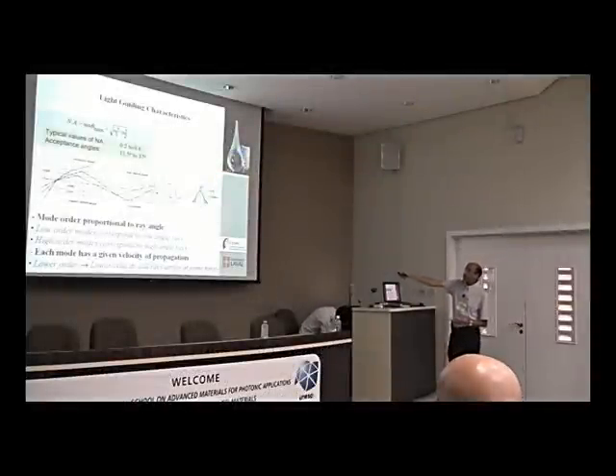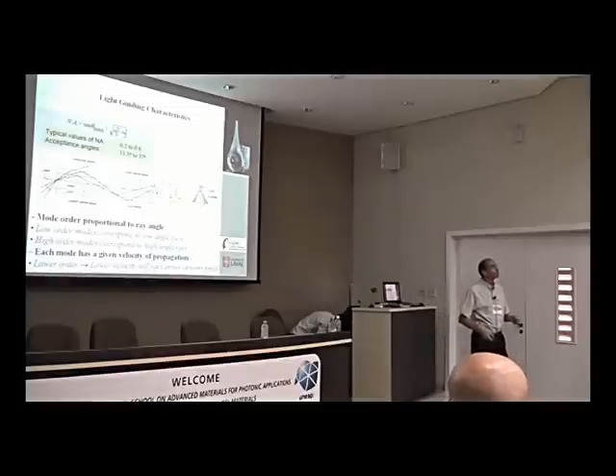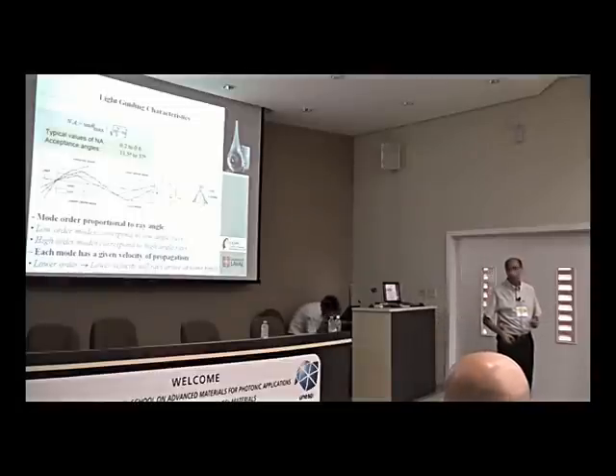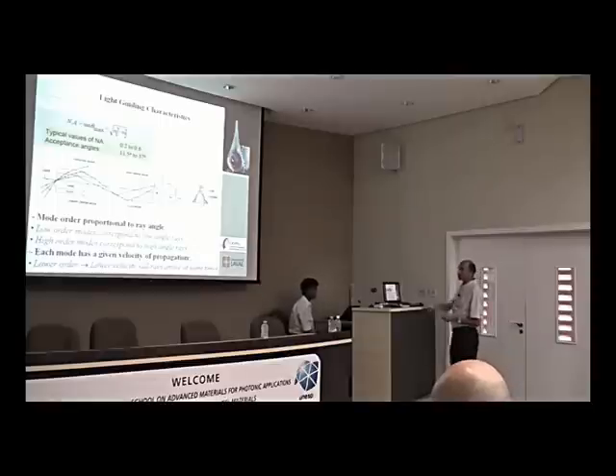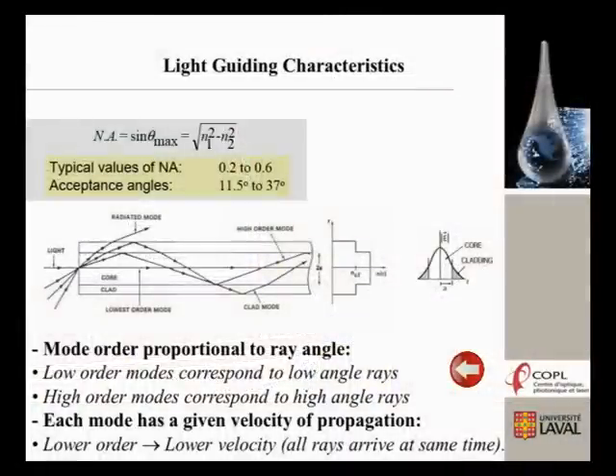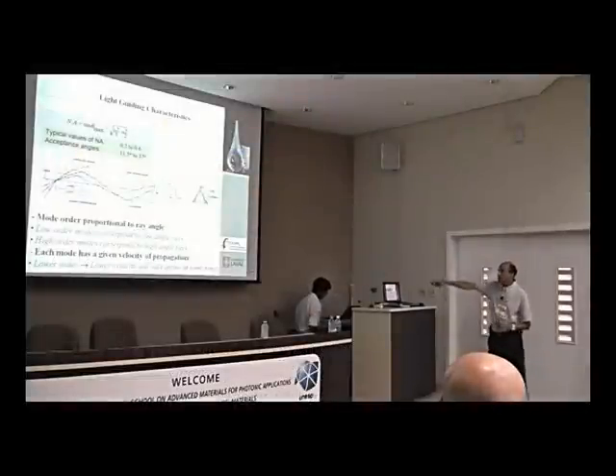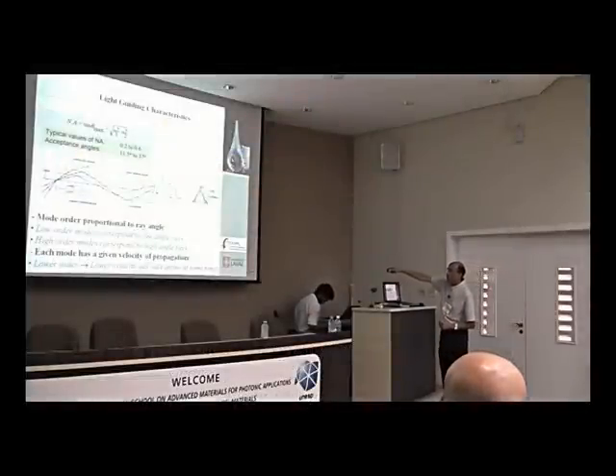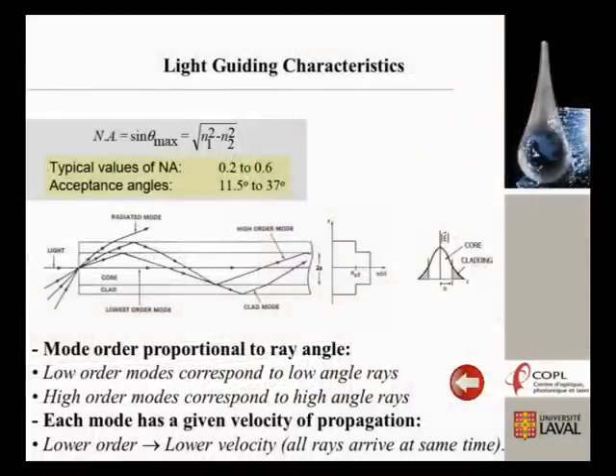And for that, what will this affect? It will affect the type of order that we get for our light inside the fiber. This is important because a low order mode will correspond to a low angle, and a higher order will get us a higher angle, higher ray. This will be each mode. It's given by the velocity of propagation of these lights inside the fiber, and this is so important for different applications, depending again on the application of the fiber that we are using.